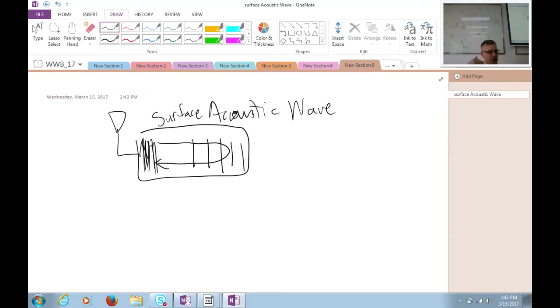In fact, I've seen people use these for temperature sensing as well. If you use lithium niobate, which actually does have a thermal coefficient of expansion that's fairly sensitive at room temperature, the shorting bars get farther apart from one another. Not that much, but enough to measure it. And because such a small difference in the mechanical world translates into such a large electrical distance, when the wave is transduced into and then out of the SAW tag, you can actually look and measure the distance between reflections and gauge what the temperature of this device is.